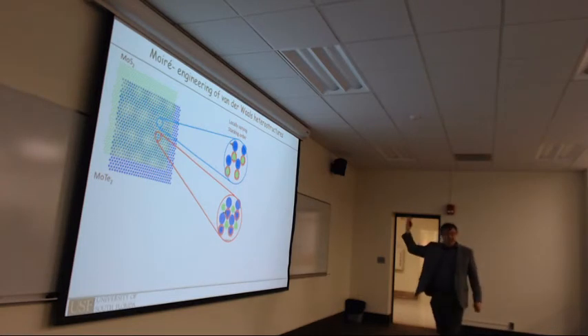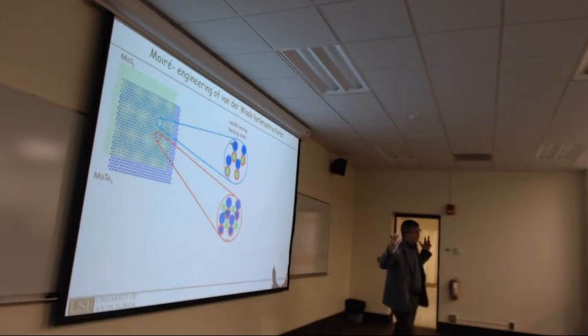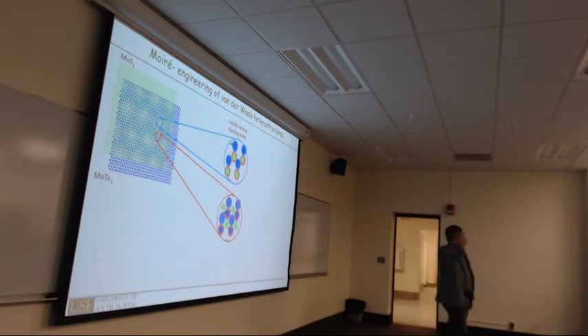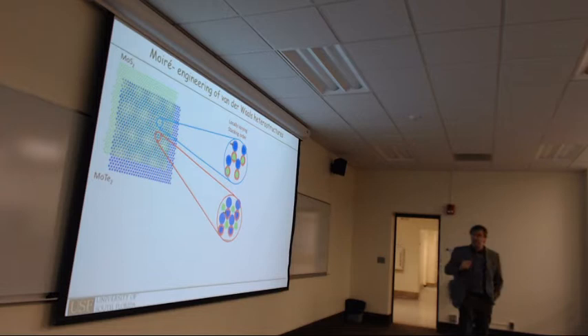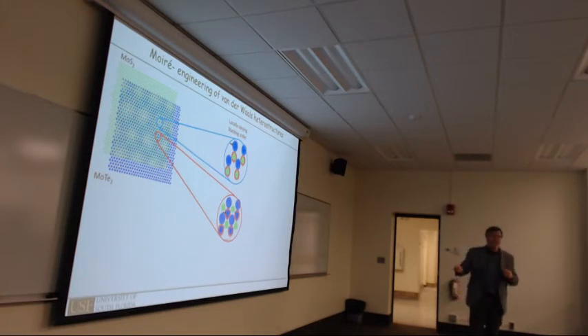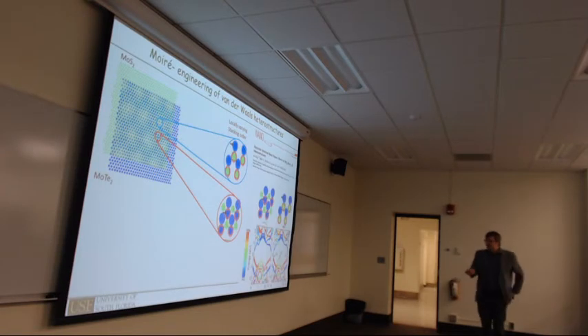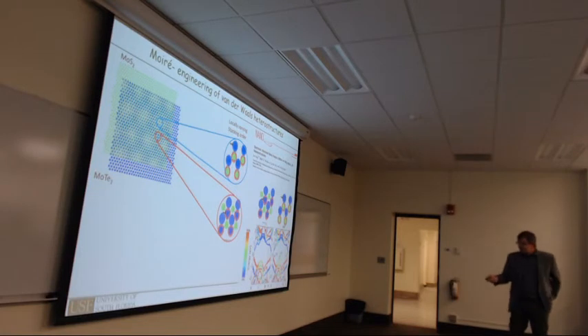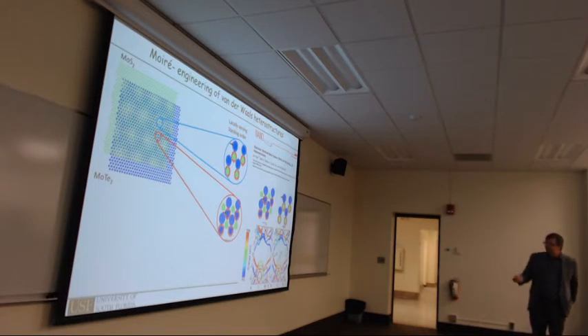Now, in the case of molybdenum disulfide, we argued that you get a transition from indirect to direct bandgap material because of the interaction of the out-of-plane orbitals. Now, the out-of-plane orbitals, of course, are fairly localized, and different orbitals from different layers will interact differently with each other depending if the atoms are just on top of each other or in a different stacking. And people have done the calculations for these different configurations. And indeed, what they see again is a strong change at the gamma point. It's the case for molybdenum disulfide and molybdenum diselenide, where in one case where you have the bulk stacking, again the gamma point is shifted up, while in this stacking the gamma point is shifted down.